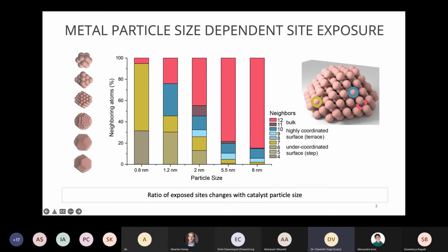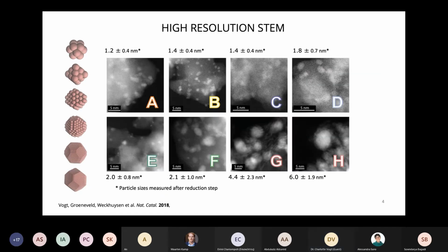And of the surface that is exposed, a lot of it is highly coordinated, or terraces, etc. For a very small nanoparticle, that changes. So a lot less bulk, and of the surface that is exposed, most of it is under-coordinated. So that explains that for those two different types of structure sensitivity, we see different behavior. Different molecules like to be cleaved by different sites.